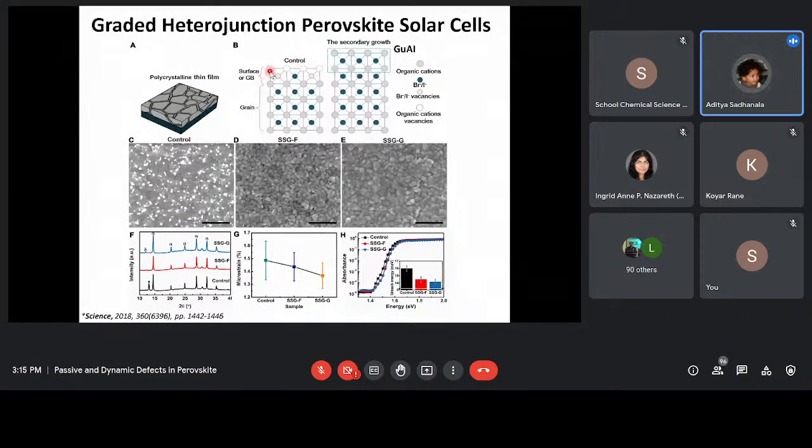It had a different cation, and that actually ended up giving us a sort of an epitaxial layer on the top, if you like. There's not much difference in the morphology as such, but we found that the strain in the crystal structure was less, where we coated this surface treated sample here, and that resulted in lower disorder. Now, how was that measured?